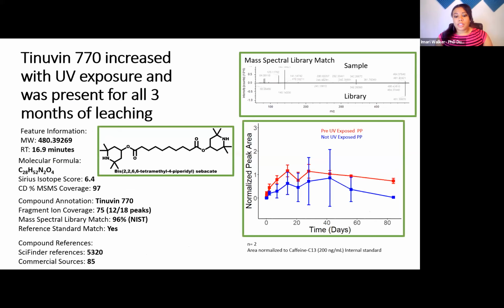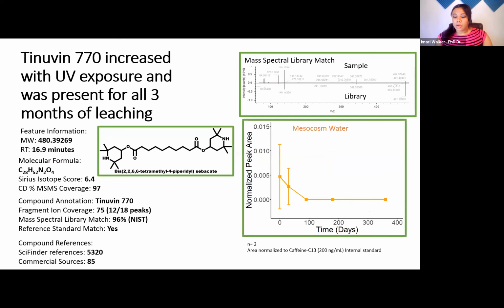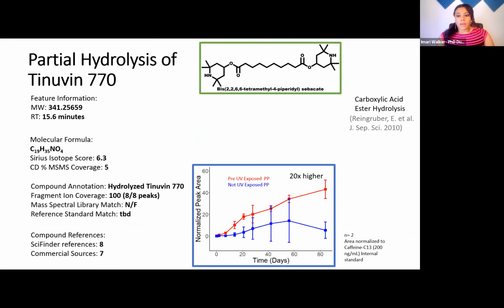Now, one of the transformations that's possible with this compound, and also within the mesocosm itself, you could see that it's present for the first 3 months of the mesocosm water, and then it's no longer seen in the mesocosm itself, which could indicate loss of the compound or degradation by microbial growth, or even absorption of the compound to organic matter itself. But it's really hard to piece that story together with so many environmental variables in a mesocosm. But another thing that can happen to Tinuvin itself is hydrolysis.